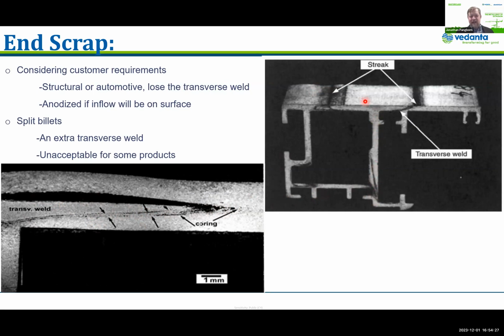And in this case, it actually shows after anodizing these very, very ugly streaks that are occurring due to that inflow. So I'm glad I have this in here, because on the flip side, we've been talking more about mechanically critical parts, but of course, if you have aesthetically critical parts, you don't want to have this inflow. The transverse weld really isn't a big deal, because you're not running a heavy structural product, but any inflow that gets onto the surface of your part through this flow mechanism is going to cause problems for sure.